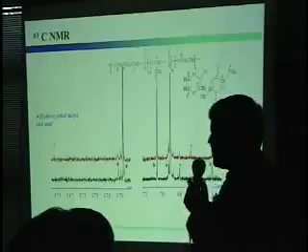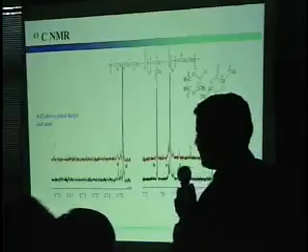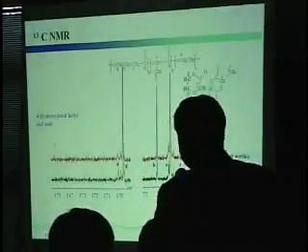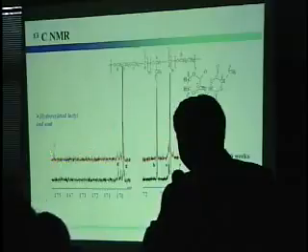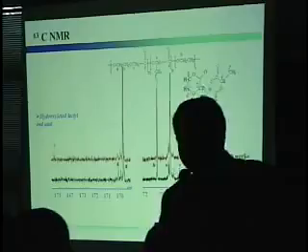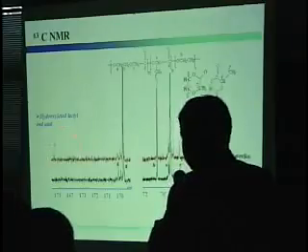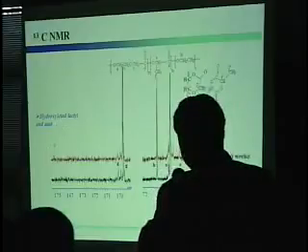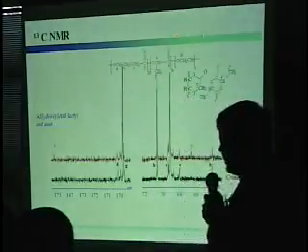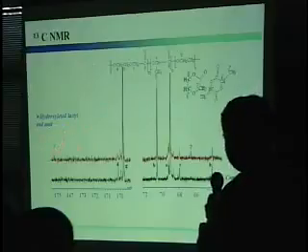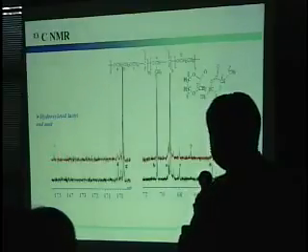This is some evidence about the hydrolytic degradation obtained from the carbon NMR. This is the control sample. Here, after 9 weeks, a new peak appeared within this range, which from the previously reported results may result from the hydroxylated lactide units. It means in the degradation time, small molecular weight fragments appear, and these appear in this spectra because of this reason.